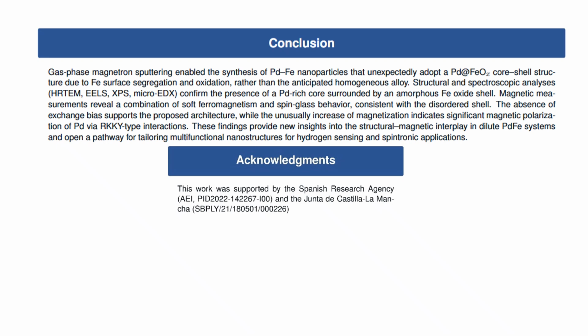So in summary, gas phase magnetron sputtering allows us to synthesize palladium iron nanoparticles. Instead of the expected homogeneous alloy, we obtain a palladium iron oxide core shell structure caused by iron segregation and oxidation. Structural and spectroscopic analysis confirm the presence of a palladium-rich core and an amorphous iron oxide shell. The magnetic measurements reveal a combination of soft ferromagnetism and spin glass behavior consistent with the disordered shell. And the absence of exchange bias supports the proposed architecture, and the change of magnetization as a function of iron suggests a strong polarization of palladium through Ruderman-Kittel-type interactions.